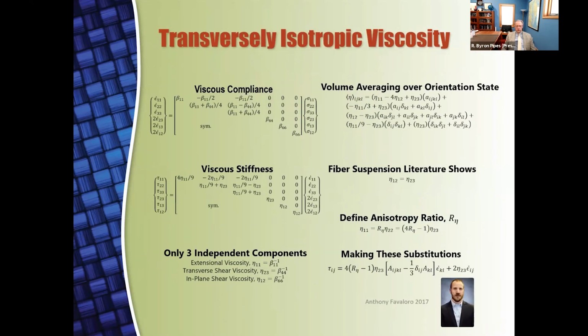I go on to talk a little more detail about the viscous compliance and the viscous stiffness matrices expanded in this form. This gives us three independent constants: extensional viscosity and two shearing viscosities, and we do orientation averaging, volume averaging rather, over orientation state. We get the form that you see there.